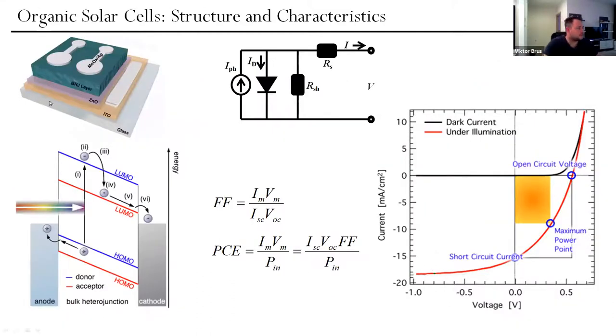So here you can see a schematic representation of a general structure of an inverted organic solar cell, where we have a glass substrate, ITO, indium tin oxide, its transparent conductive layer, and an electron transport layer, which is here a zinc oxide layer. It's also spin coated on ITO, which is magnetron sputtered on the glass substrate. Then we have the spin coated so-called bulk heterojunction layer, which is a mixture of donor and acceptor organic semiconductors. We will discuss this in more detail on the next slide. And also a hole transport layer and back electrode, which are necessary to collect holes. So electrons are collected by zinc oxide and ITO.